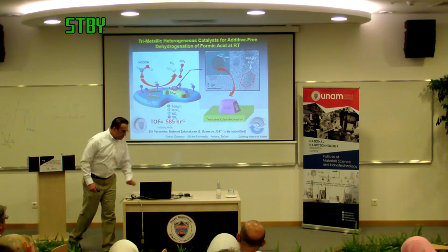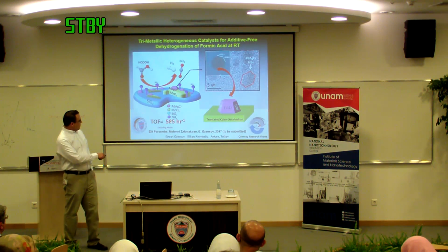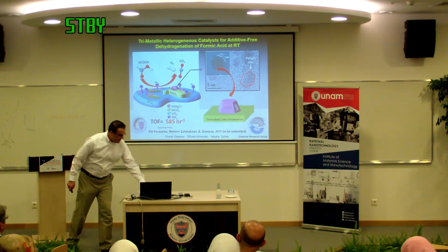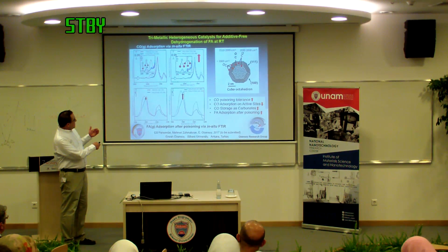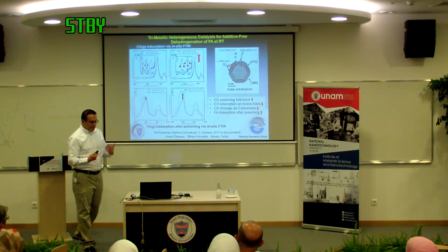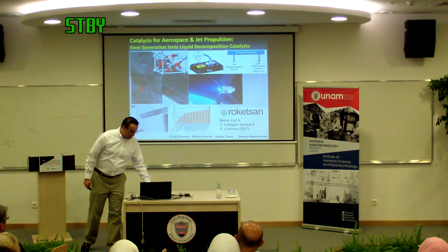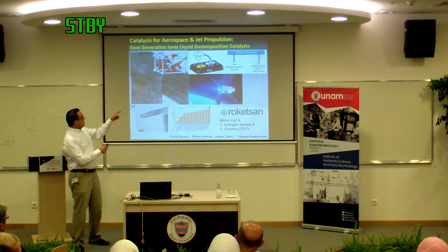And now we've even taken the game one level higher. We made trimetallic engineering of these catalysts, and now we've got the record high material again. This is to be published hopefully next month. And by using spectroscopy, you can see that the CO adsorption is going down significantly, and also frequencies are shifting, which is an indication of CO adsorption strength going down. We can say that this catalyst is less inclined toward CO adsorption. And you can see this is not rocket science, these are simple things, right? But this is rocket science.